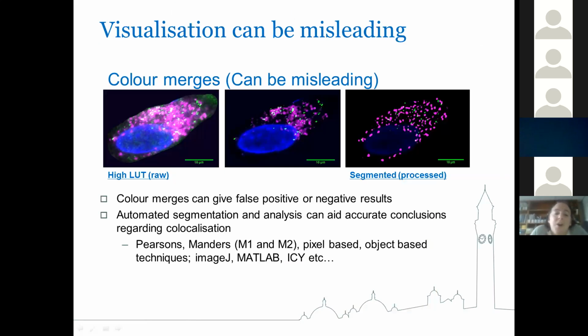It's important to know, though, that that visualization can be misleading. So this is the color merge. So this is the overlay of all the different channels. So the LysoTracker channel, the DAPI channel, the RAB staining, and so on. Whereas if we deconvolute those and segment them, we can see much more accurately where the particles are. So with some of these, it might look like there's particles in the nucleus, but for example, when we deconvolute it, they're actually either in the layers above or below. They're not in the nucleus.